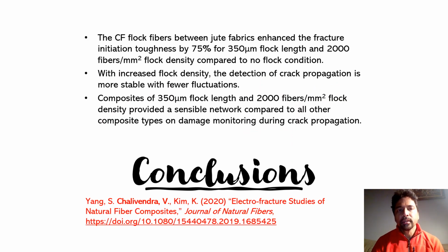So to conclude this study, the carbon fibers addition between the jute fabrics enhances the fracture toughness by 75% for a system of 350 micron length and 2000 fibers flock density compared to the non-flock condition. And also with increasing flock density, the crack propagation is more stable with fewer fluctuations and less noise. And composites of 350 micron length and 2000 fibers per millimeter square flock density provided a sensitive network compared to all other composite systems for damage monitoring during the crack propagation. Hence, we recommend using that system in real life applications.